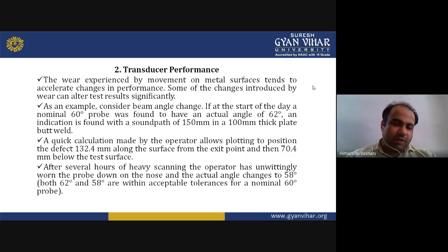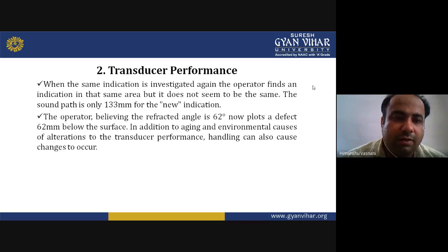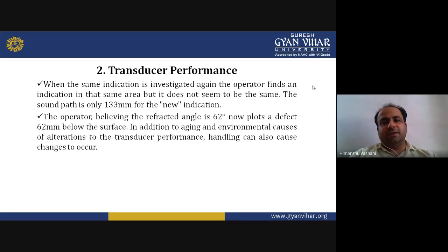After several hours of heavy scanning, the operator unwittingly wore the probe down on the nose and the actual angle changes to 58 degrees. Both 62 and 58 degrees are within acceptable tolerances for a nominal 60-degree probe. When the same indication is investigated again, the operator finds the indication in the same area, but it does not seem to be the same. The sound path is only 133 mm for the new indication. The operator, believing that the refracted angle is 62 degrees, now plots a defect 62 mm below the surface. In addition to aging and environmental causes of alterations to the transducer performance, handling can also cause changes to occur.